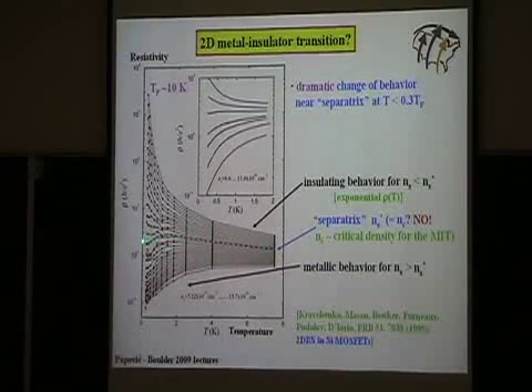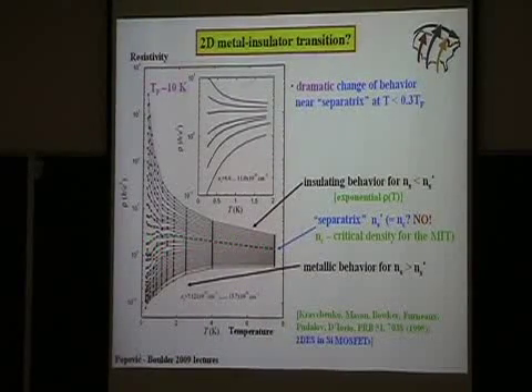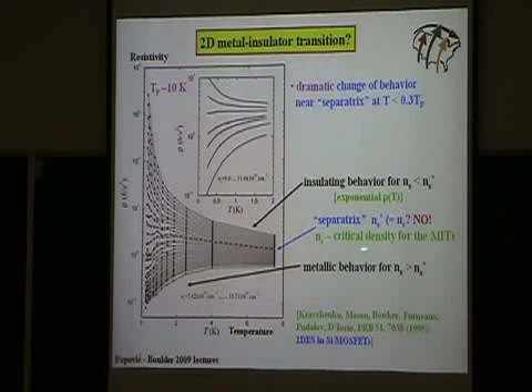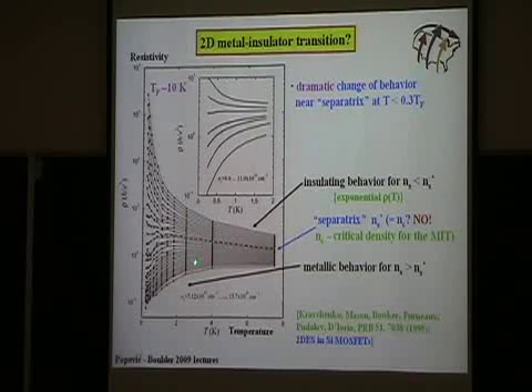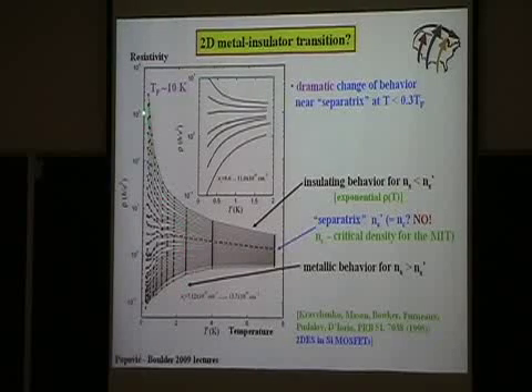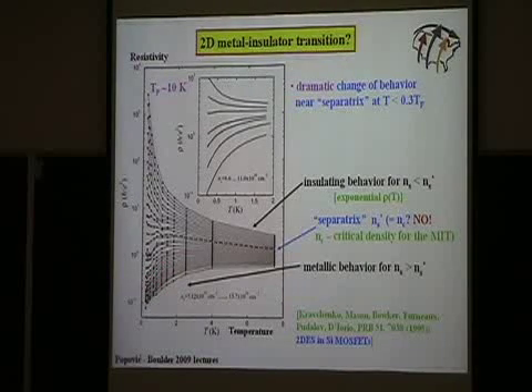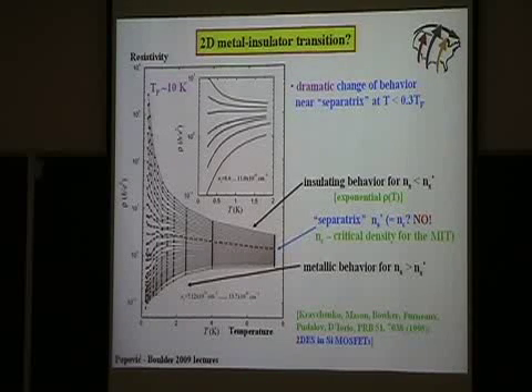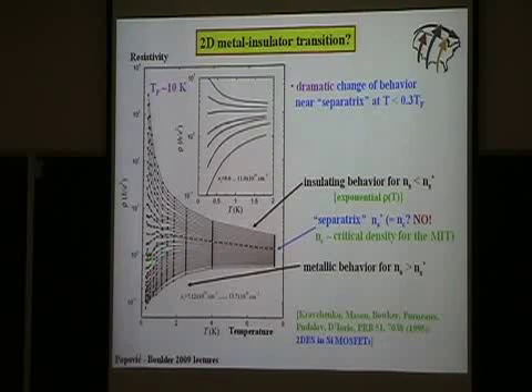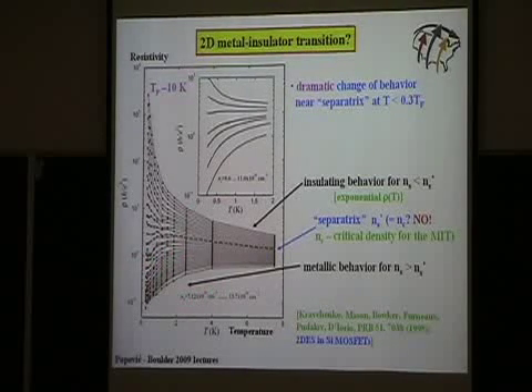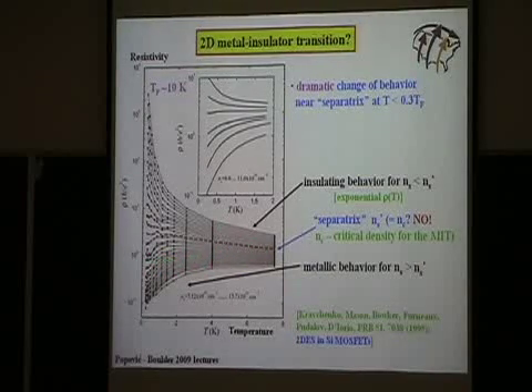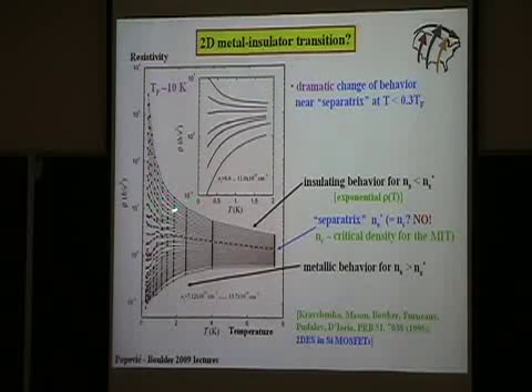Many people thought that maybe this corresponds to the critical density, even though in some cases it is not true in general. I will say more about this tomorrow. The point is that at some low enough temperature, there is a dramatic change in the behavior. See, these curves all go up, and these curves go down for different densities. Somebody asked a question about scaling. These curves look similar, so you may imagine that if you shift them this way, they might collapse, and these curves also look similar. If you shift them this way, they might collapse.